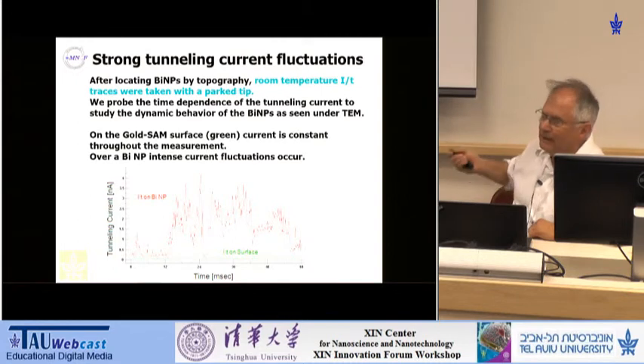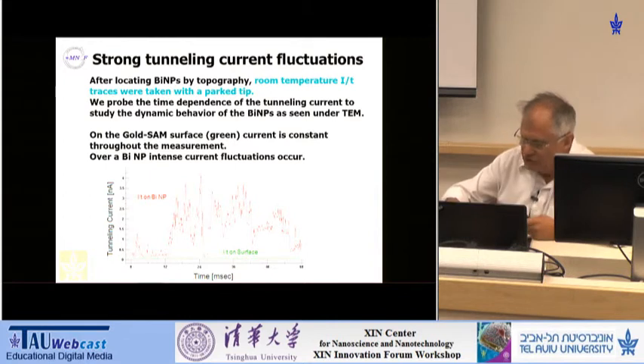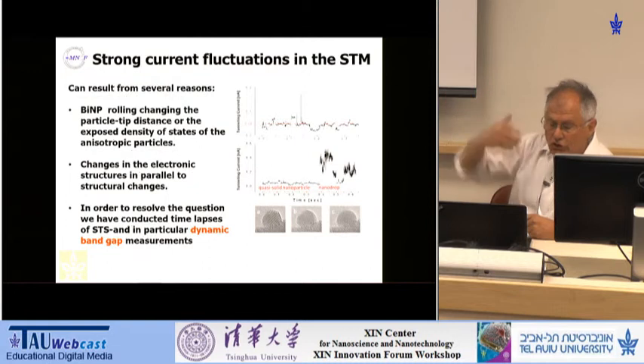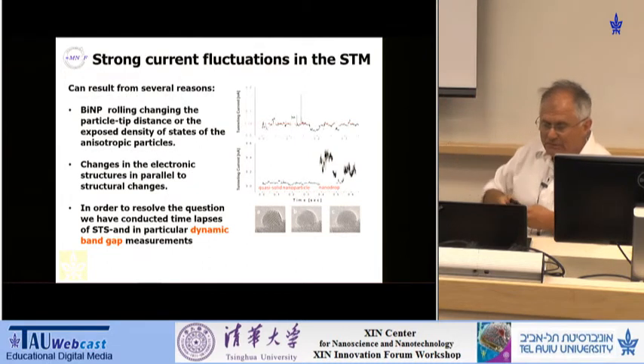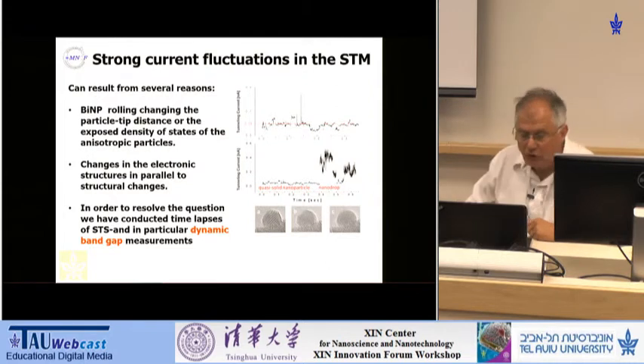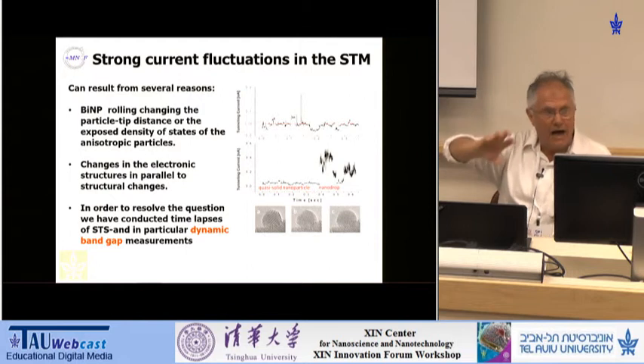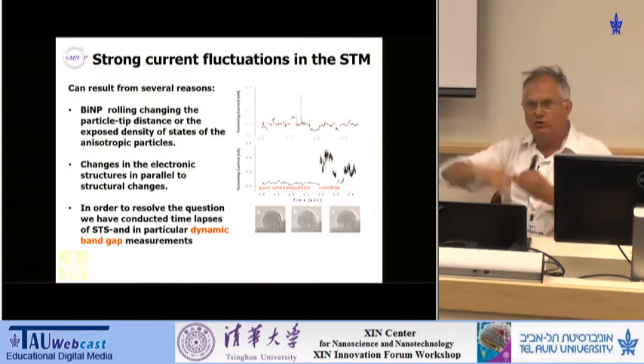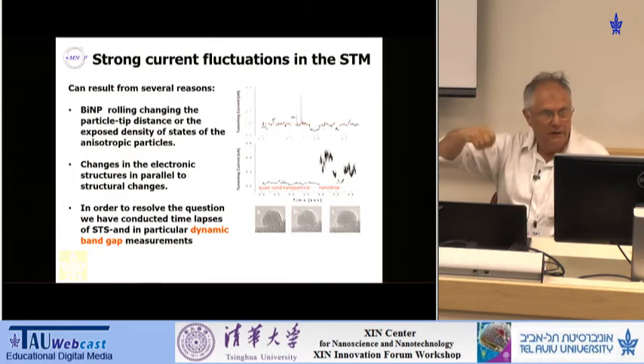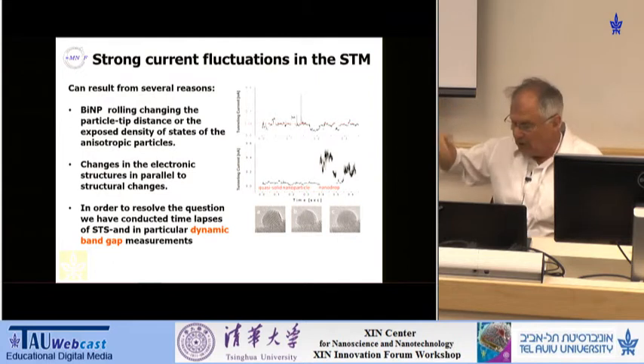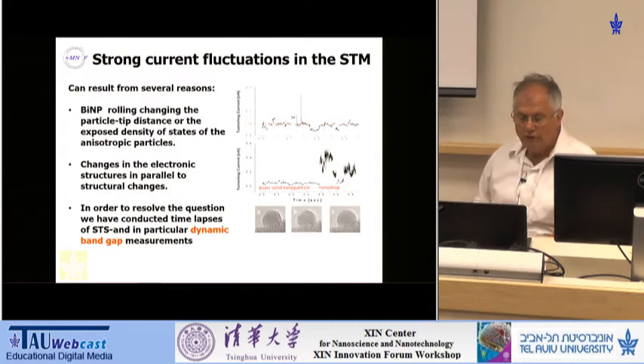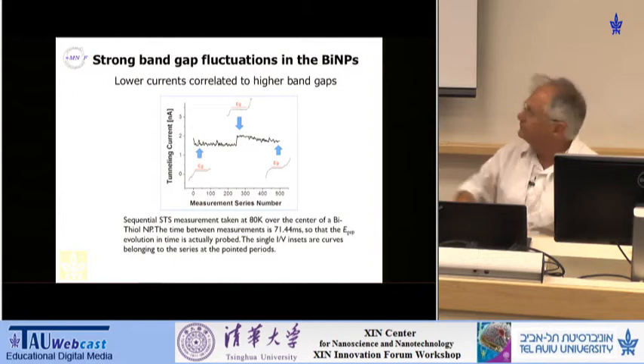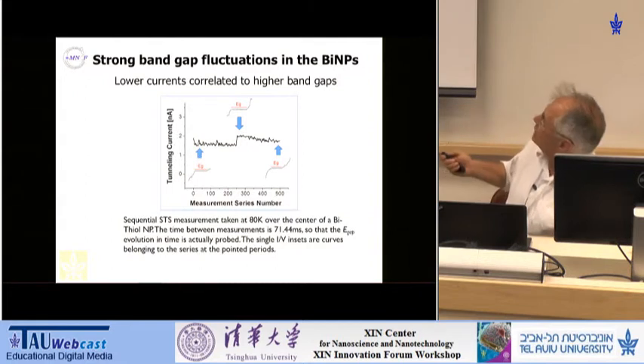But as we stand on the other particles, we have very erratic changes in current. So it's not only that the picture varies, but also the properties vary. But that can originate for two reasons. First, the particles can roll and get closer or farther from this particular needle. And if that happens, one would expect fluctuation in the current. But the other possibility is that indeed there are changes in the electronic properties of these particles. And to check that, we have to measure the band gap of the nanoparticles, namely this plateau that you see here, and how this plateau changes with time.